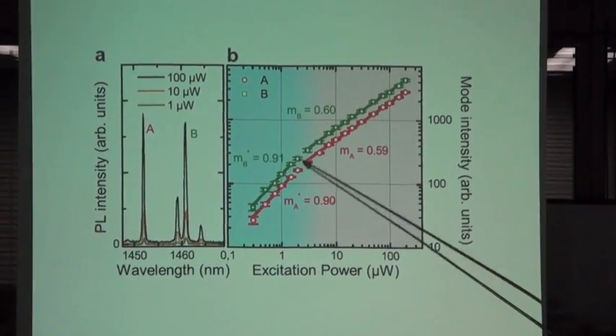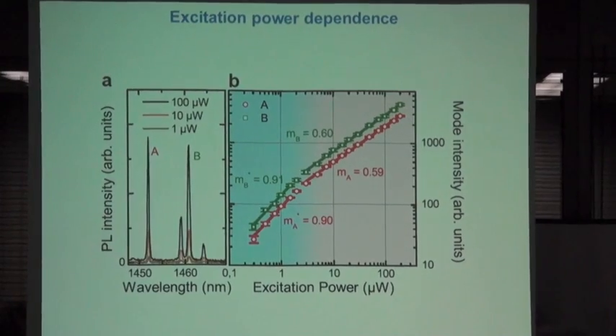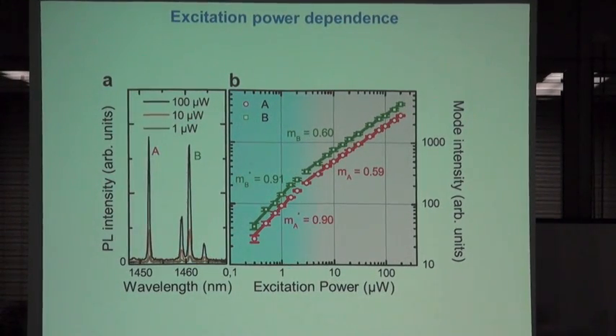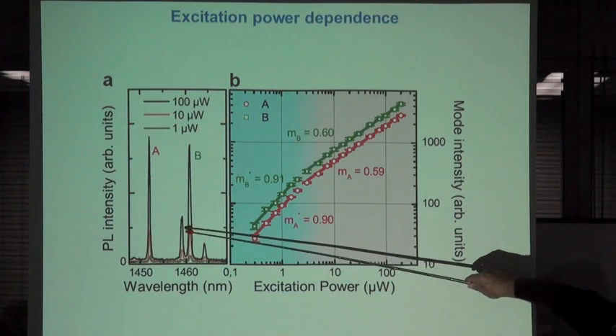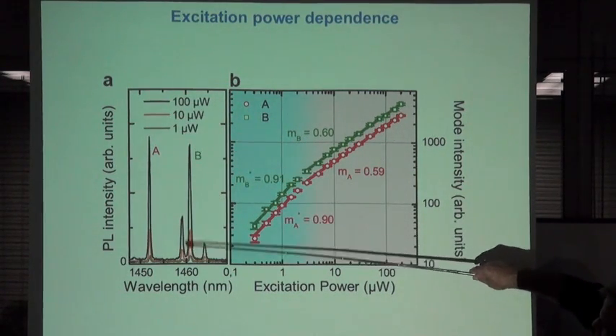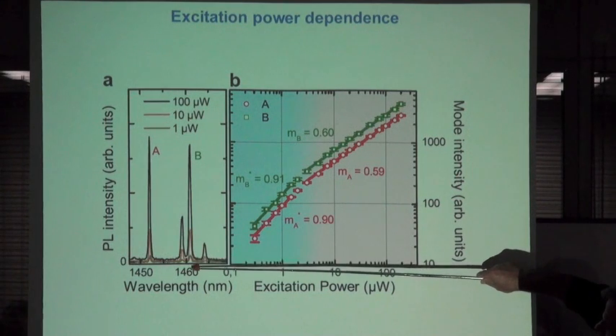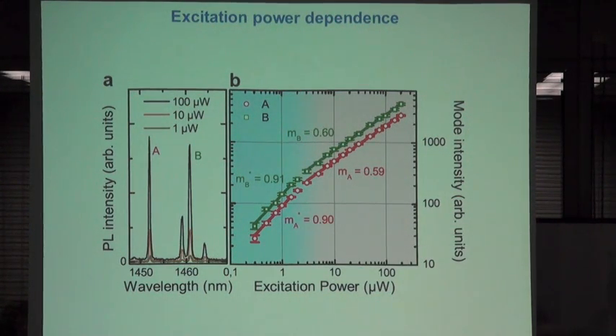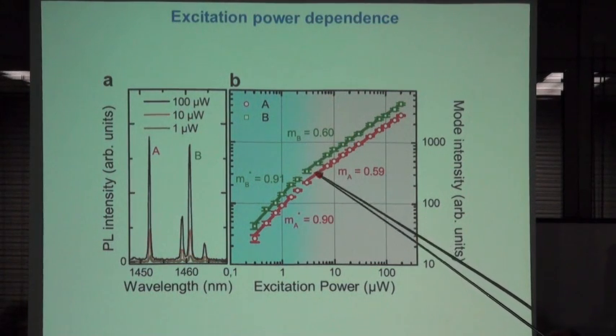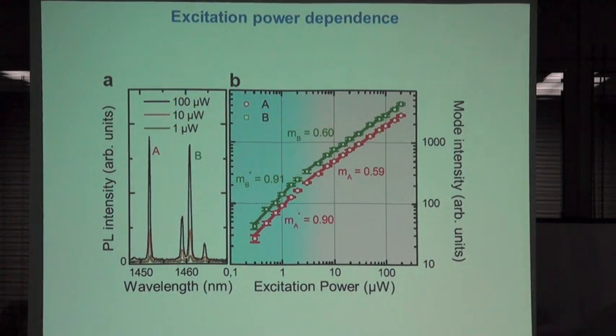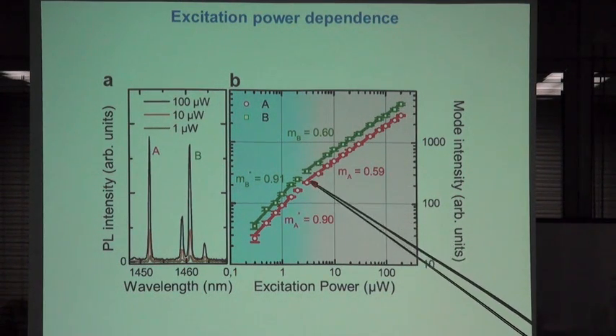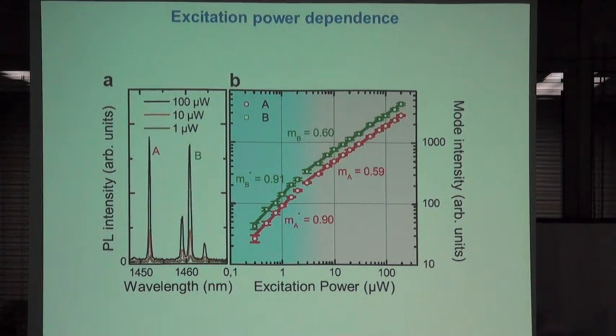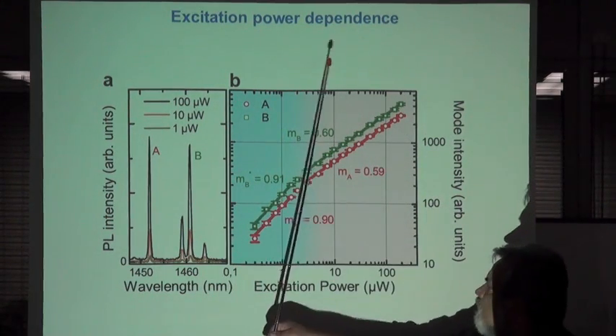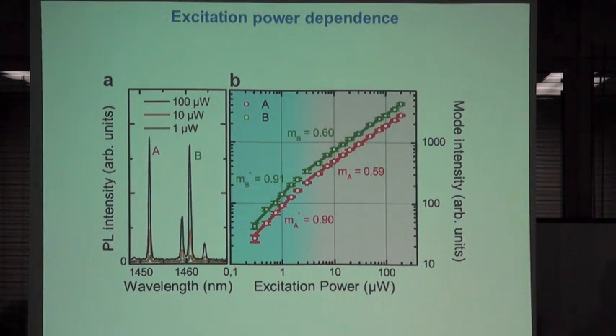Now when you plot this, in this photonic crystal we could go down much lower in excitation, so we have a very low excitation power of less than a microwatt here. And what we see is these are the modes A and B here at 1 microwatt, at 10 microwatt excitation and 100 microwatt. You see Q is not changing. And the intensity is in the beginning going linear, and then it's more like 2/3, which indicates that we have here indeed radiative recombination, and here maybe Auger effects or non-radiative recombination plays a role, and then you go away from the slope roughly 1 here.